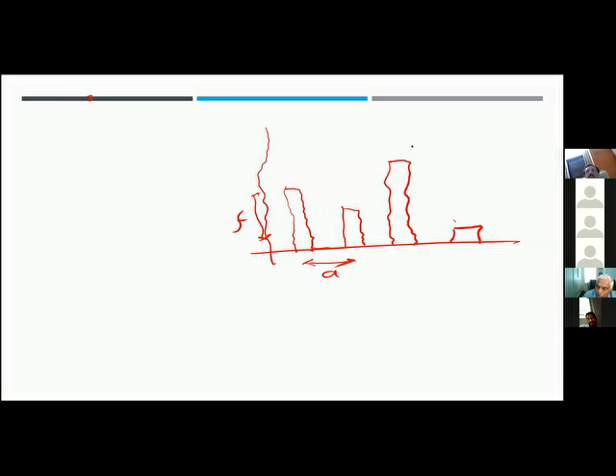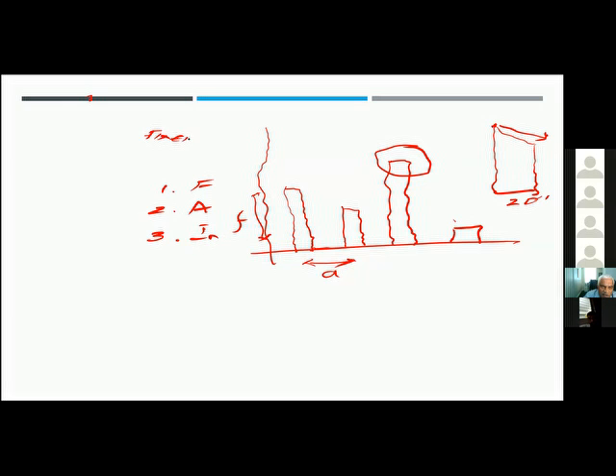And also, if I take this top part of the graph, it will actually be like this. Which means I can start at a certain flow and then drop the flow for the rest of that period of, say, 20 seconds or whatever it is. So I have three parameters. I can adjust frequency, I can adjust amplitude, and I can adjust the incline or slope, as we call it. So I am first giving a fixed mass of carbon.